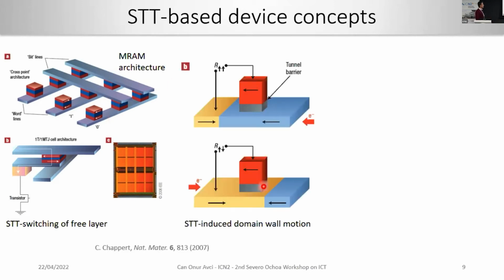You can also use an alternative geometry using domain wall motion. So basically, you are still talking about the same kind of MRAM, like a spin MRAM architecture, but this time, okay, this stopped working, unfortunately. So this time you can move the domain wall underneath that tunnel barrier and change the relative orientation of the magnetization between these two magnetic layers. And this can also be another way to basically control these spin torque MRAM devices.